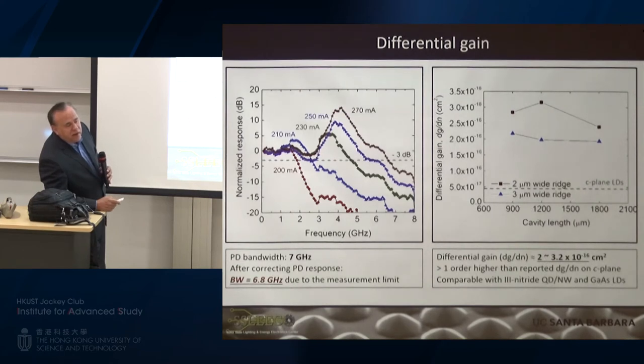If you leave the diode biased at that condition for a prolonged period of time, say an hour or two, does it actually degrade due to self-heating? You know what? We haven't tested the speed as a function of time, but our lasers don't degrade over 10,000 hours. But what I haven't checked... Do you CW drive it? What's that?